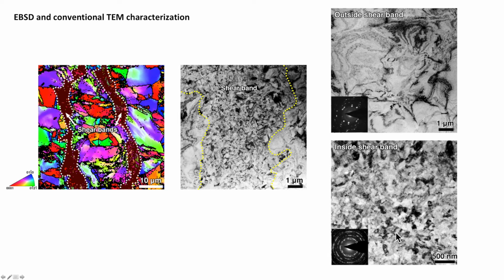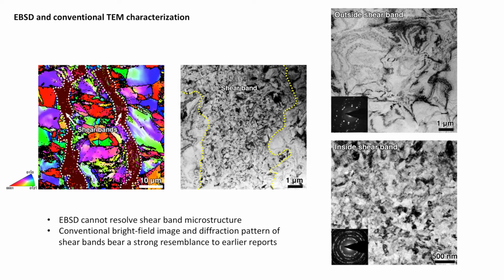Here is a TEM micrograph that captures a shear band as well as the regions outside the shear band. When we did electron diffraction in the region outside the shear band, you can see individual diffraction spots, telling us it is more or less still a coarse grain structure. Then within the shear band, you see diffraction rings that tell us there are a lot of nanocrystalline grains within the shear bands, which seems to support the dynamic recrystallization hypothesis we mentioned earlier in the presentation. As TEM microscopists, we know that the diffraction contrast in TEM is extremely sensitive to the exact tilt of the crystal. Even 1 degree of reorientation can lead to a dramatic change in the contrast.